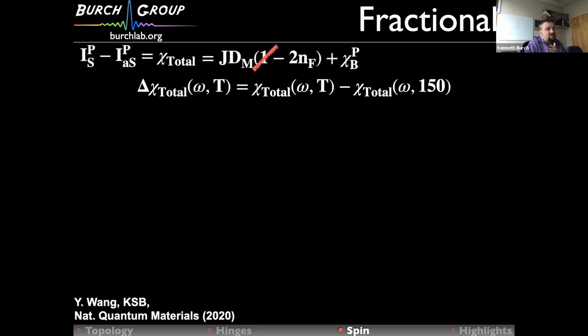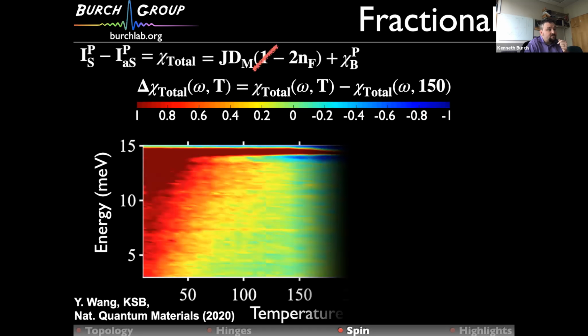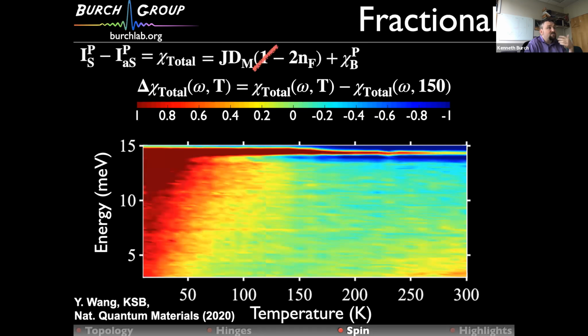Okay, so we just subtract off this sort of temperature independent part. And this is what I'm showing you here. The red is where we see enhancements in the Raman susceptibility, and the blue is where it goes down. So the sharp feature you see close to 15 meV, that is just a phonon, so that's why it doesn't do anything particularly interesting. This broad feature at low energies and temperatures, that's the magnetic continuum, coming from these fractional excitations.